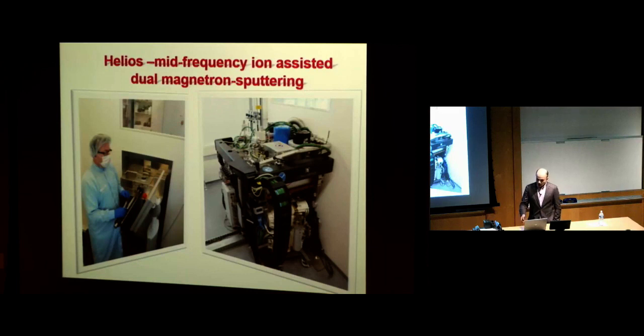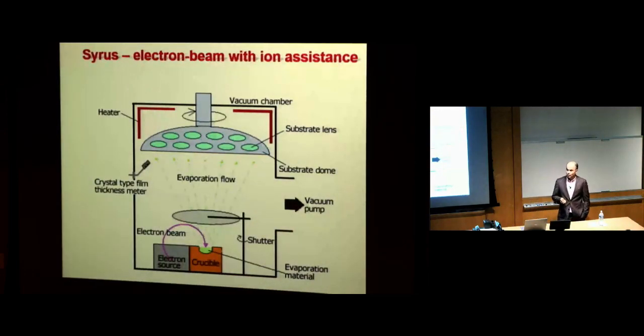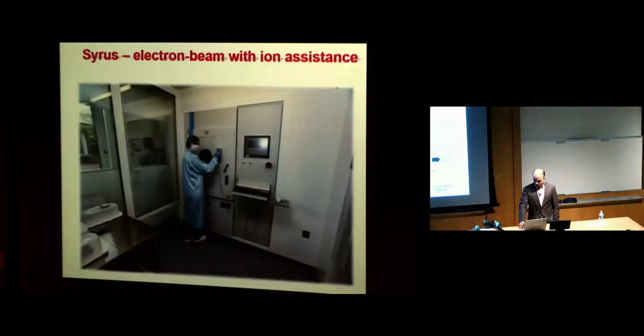This machine provides very great precision, but I will come back after comparing all the techniques we have. The oldest technique is the so-called electron beam machine. There are different variations of this machine. It might be with ion assistance, without ion assistance, and so on. But the basic principle is that we have a material, and with an electron gun we send electrons to the material. The electrons are accelerated and bring energy to the material, and we evaporate the material in such a way.